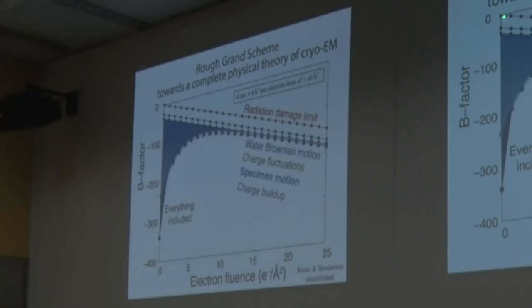live with it. So the idea is that if it's perfect, the first image that you take will have a B factor of 0. And then as you introduce radiation damage and go to an exposure of 25 electrons, you gradually, and we think it's around 5, 6, 7 B factor per electron per square angstrom, it goes up and up, and by the end here, you've got a B factor of about 150. And then what we're getting in these structures, initially we had terrible other reasons, but at the moment we're in about here. And the reason, because the top of this curve is in that region.